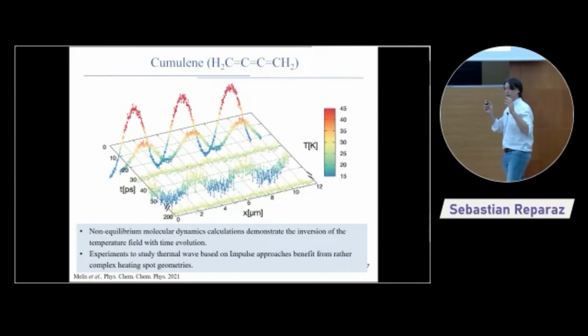If one is critical and says, okay, what is the definite proof that you have waves there? Only these oscillations. That's not good. So what they did is a very beautiful figure for me. Here you see the initial thermal landscape, and in this direction, time starts elapsing. After some time, you have a decrease of this, and close to 30 picoseconds, you have no more signal whatsoever. The temperature is stable.